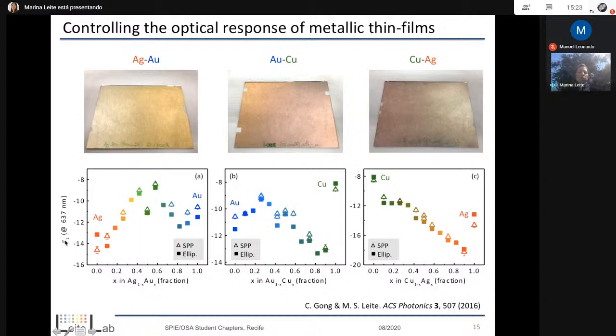So essentially here you're seeing epsilon 1 at one particular wavelength, 637, as a function of chemical composition for each one of the samples. The solid square is the ellipsometry measurements, meaning transmission and reflection combined, and the SPP is in Kretschmann configuration. There's a very non-linear combination behavior, right, of the two as a function of chemical composition. For copper and silver it is almost linear, but in this case, we do have a material that is not fully alloyed. There's a lot of segregation in the material.